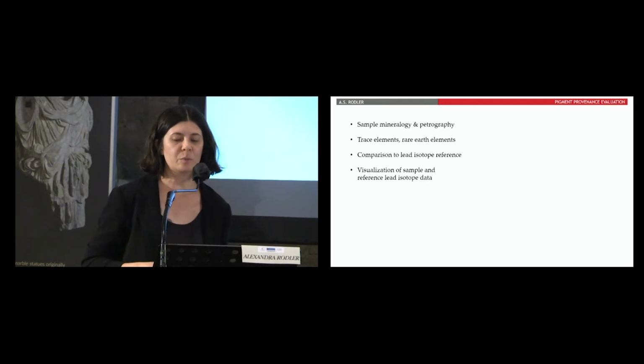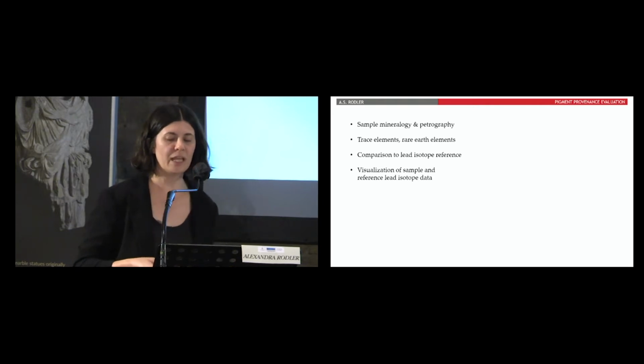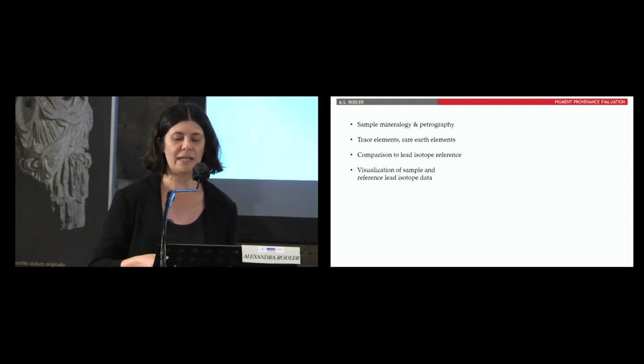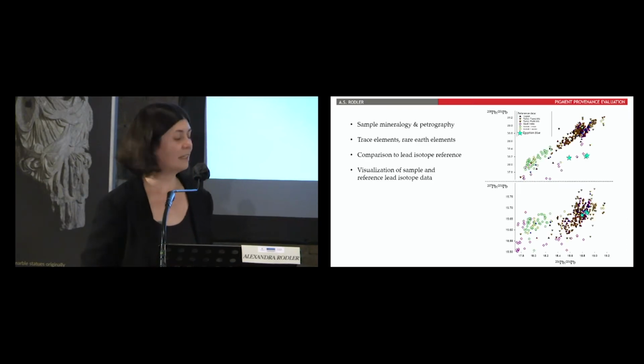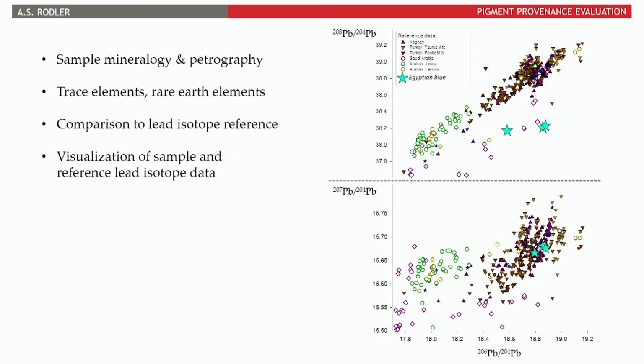Besides the mineralogical and petrographic information, we also include trace elements and recently also rare earth elements to support the lead isotope-based provenance evaluation. The sample lead isotope data is then compared to large lead isotope databases where the least likely source areas are excluded, as I said before, and the matching source areas are then plotted with lead isotope biplots, like you can see here now. So I will not bore you too much with the basics of this, and you're very welcome to ask me later. But what you can see here, usually we have lead 206 over 204 on the x-axis, and then lead 207 and 208 over 204 on the y-axis. So it's usually in this double plot.